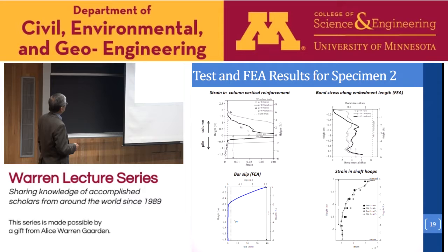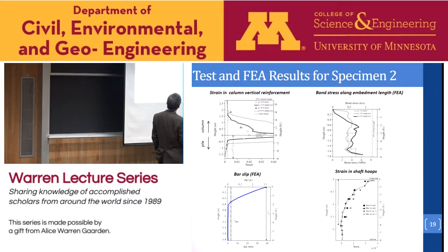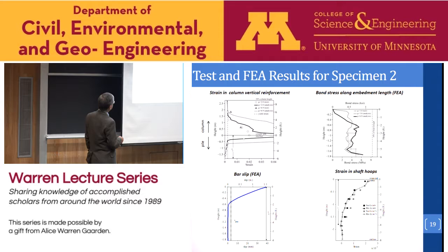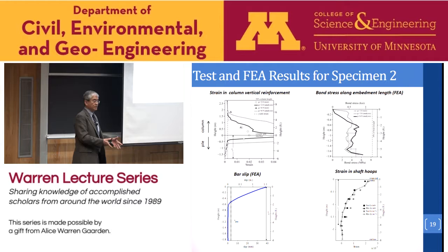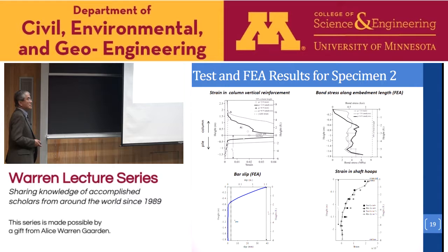Now, this is something we obtained from the model. We could not obtain it from the test. This is the bond stress along the depth. You can see two situations: the gray shows ductility of 3, and this shows ductility of 6.9. In this comparison, you can see the gradual bond degradation along the bar near the interface between the column and the shaft. Initially, we have this bond stress distribution. After a number of cycles, the stress here dropped because of plastic strain penetration into the shaft and as a result of the bond degradation. In most of these tests, we found the plastic strain penetration to be around maybe 10 times the bar diameter.